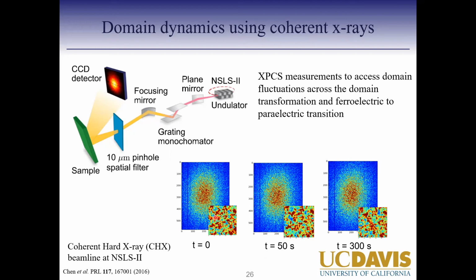If instead I had incoherent X-rays, which is what we have in our lab source, then you will basically have this interference for each coherent bucket, if you think about it. And then if you average over all, you'll get a very nice homogeneous Gaussian peak, which is what we are used to seeing when we measure our materials. We see a very nice Gaussian Bragg peak, but that loses out all the speckle information. And these speckles are directly a manifestation of what sort of inhomogeneities are present in the sample. And depending upon which Q value we are in reciprocal space, we can track Q-dependent dynamics in the material, so how each length scale is behaving, okay? So this coherent X-ray scattering gives you very valuable information about length scales in your sample.